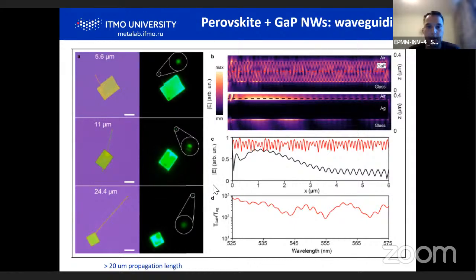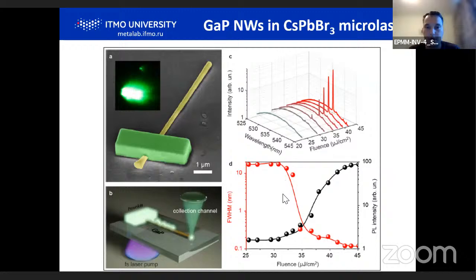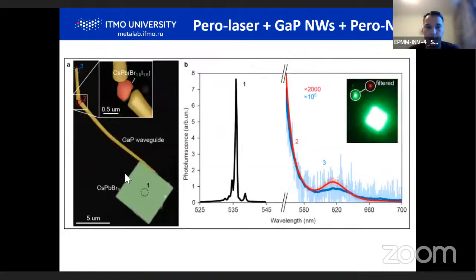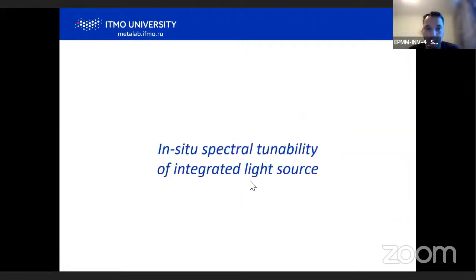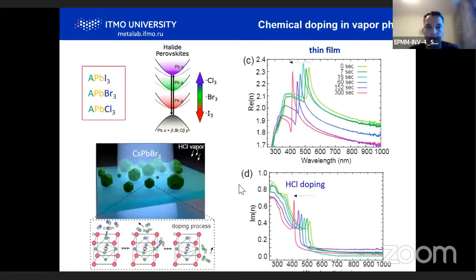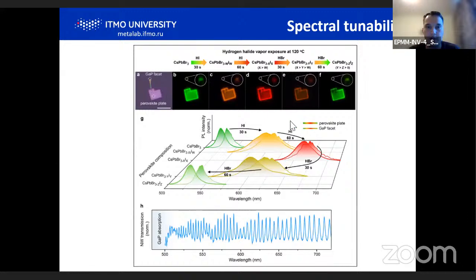As you can see here, some examples of integrated nanowires in micro lasers. And then we integrate them even with other perovskite nanoparticles and other waveguides. And these lasers also can be tunable due to this anion exchange reaction. And you see here that in vapor of acids, we can just reversibly tune the color of such lasers, which is quite unique among the semiconductors.